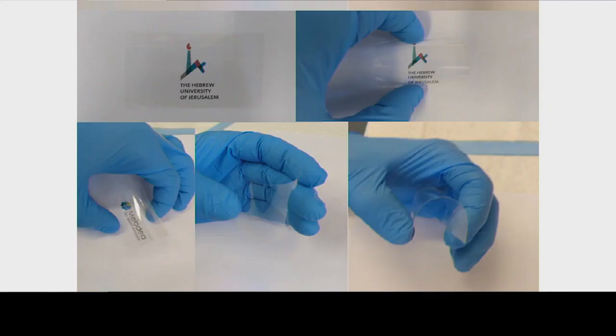So what can you do with that? In fact, a lot of things. But all these things that you can do with nanocellulose boil down to one very simple fact, and that is, just like any other nanobiomaterial, these fibers like to self-assemble. So above a certain concentration, when they are suspended in water, 2.5% or 3%, they start to form this chiral nematic liquid crystal structure. So once you apply that on any surface, can be a plastic or wood or whatever, or concrete, it will self-assemble and will form a very, very strong and transparent film.